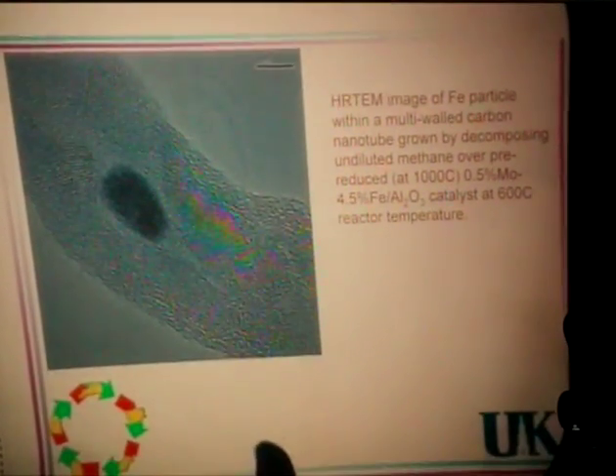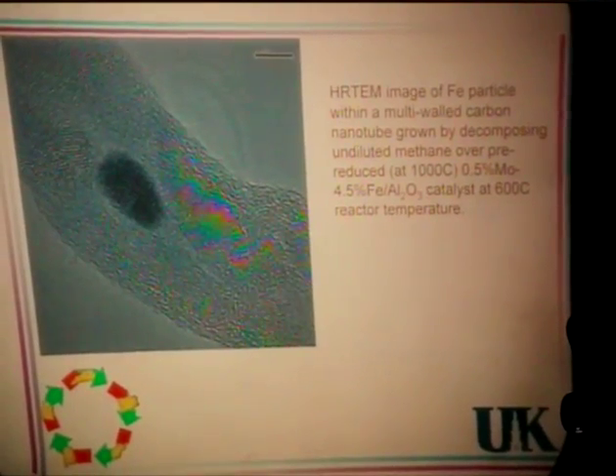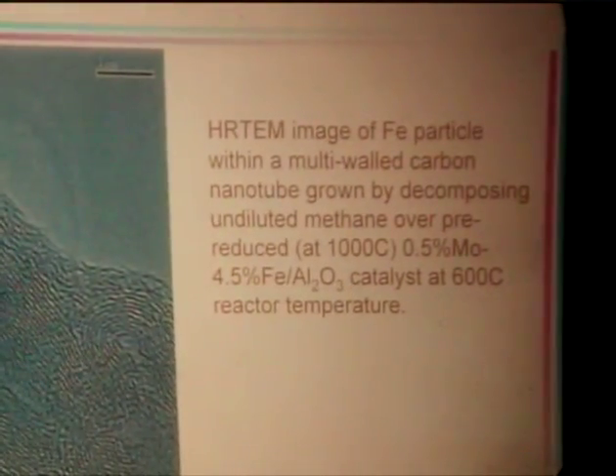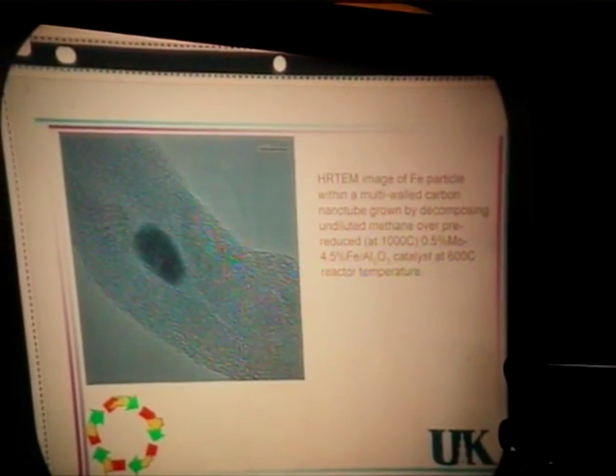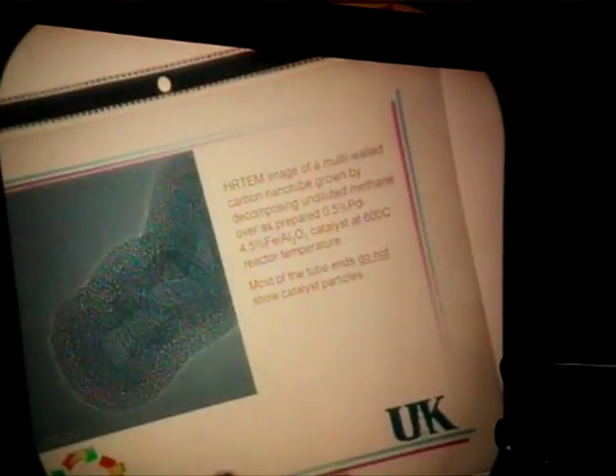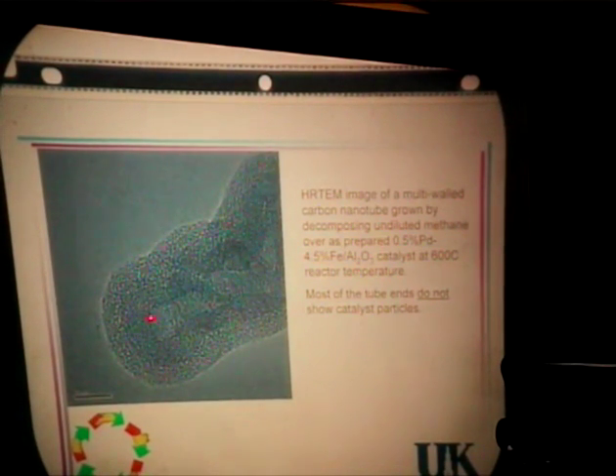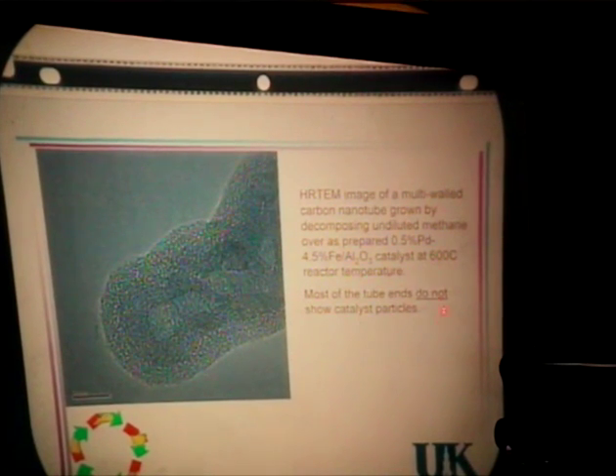A high resolution TEM image shows the graphitic layers, and there is an iron particle in between the layers within the multi-wall nanotube. This is grown over the moly iron catalyst at 600 degrees centigrade. In our cases, the multi-wall carbon nanotubes do not show any catalyst particle. Most of the tube ends do not show a catalyst particle.